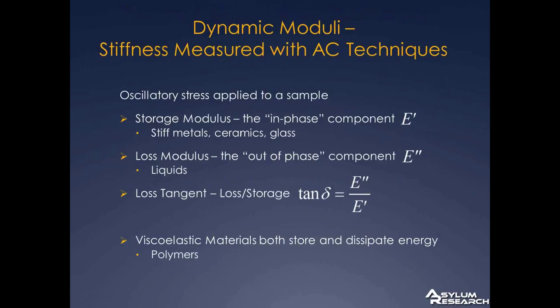In AC and tapping mode, since we're hitting the sample with a periodic force, it makes sense to talk about the dynamic moduli. In other words, instead of talking about Young's modulus as a time-dependent quantity, we're going to move into frequency space and talk about the frequency response. In frequency-dependent moduli, we imagine applying an oscillatory stress to the sample, and at the same frequency, there's a response. The response can be in phase, in which case you're measuring the storage modulus, or out of phase, in which case you're measuring the loss modulus.